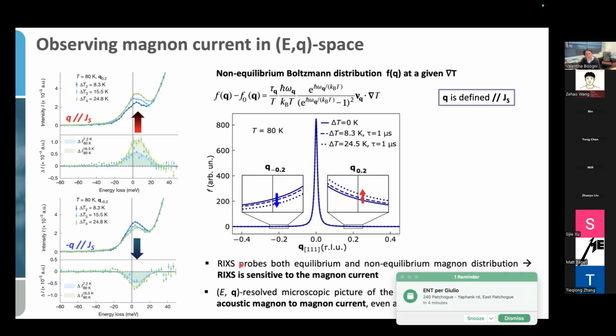So we can straightforwardly conclude that RIXS probes both equilibrium and non-equilibrium Magnon distribution, and it is sensitive to the Magnon current. And more importantly, because we have this energy and momentum selective probe, we are identifying the Magnon mode that is contributing to the transport. And we conclude that the acoustic Magnon then has a key role in the Magnon transport phenomena, even at a finite Q. That is what we measured in this experiment here.